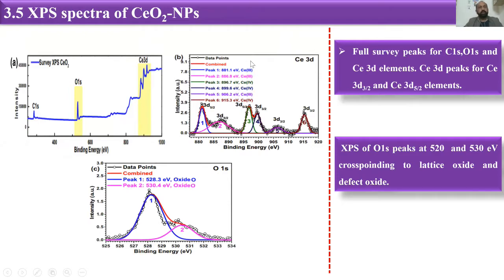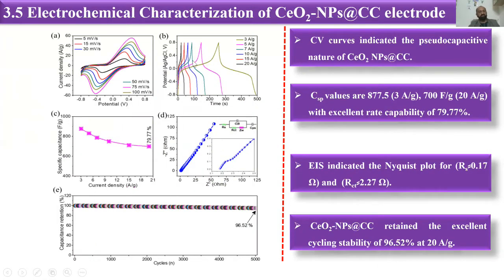Then we have done the electrochemical characterization of our cerium nanoparticles. And again, we have got the CV curves of the pseudo-capacitive materials, and our GCD curves are also of pseudo-capacitive nature. So we have calculated the specific capacitance of our cerium nanoparticles, which is about 875 point something, with the rate capability as well. Again, we have done the EIS spectra, and the cyclic stability of the cerium nanoparticles is also remarkable, about 96.52%.